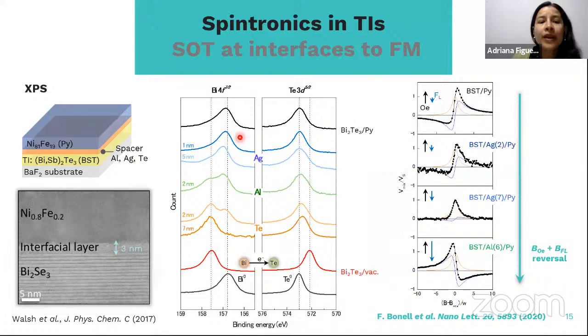We used another characterization technique, which is X-ray photoemission spectroscopy, in order to study what is going on at that interface, and then we were able to correlate that contribution, mostly from the field-like torque, with the improvement of the interface when we use that spacer of aluminum.